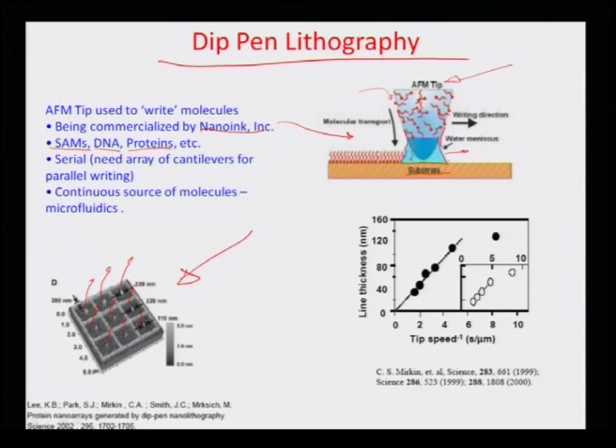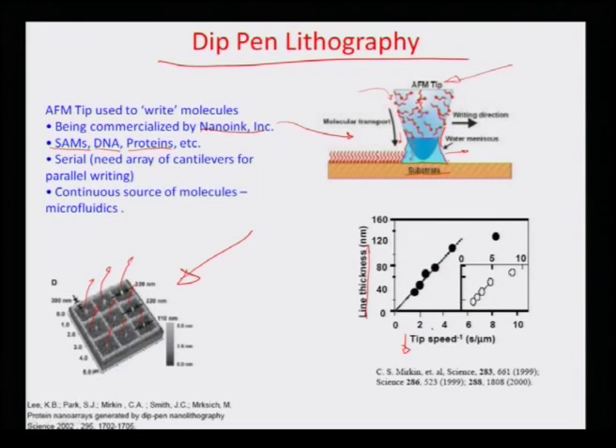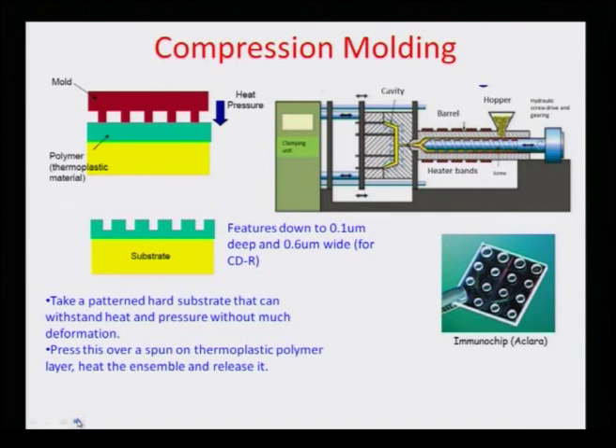The line thickness of molecules deposited is directly proportional to the inverse of the tip speed — meaning if the tip speed goes down, line thickness goes up, because there is more dwell time of the tip at a particular place. That is the fascinating process of dip pen lithography, another soft lithography technique that can write soft molecules onto a surface using an AFM pen.